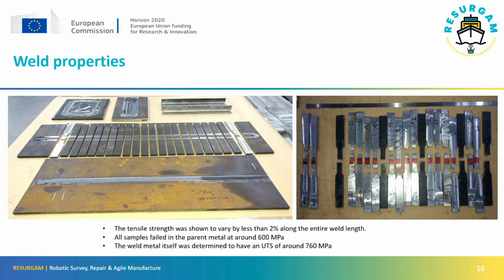The image also shows that we've done the welds in plates where we've actually prepared the weld zone carefully. So we've cleaned off any oxides, any paint, we've removed any rust and done the welds. But we've also welded some plates where we left the rust on them, we've left oil on them, we've left all kinds of contaminants on them to find out, is this process something that you can use industrially and not have to spend a lot of money making sure that your work pieces are perfect. And what we're finding is that the welds we've made in dirty, rusty, oil-covered plates are just as good as those that we can make in a plate that's had the edges milled.